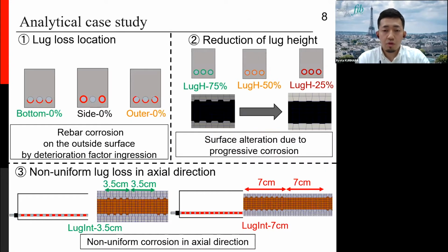To investigate conditions closer to actual corrosion, three viewpoints were considered: the lug loss location, the reduction of lug height, and the non-uniform lug loss in the axial direction. Case 1 supports the corrosion process. The rebar corrosion is caused by the penetration of deterioration factors from the concrete surface. Therefore, the rebar corrosion starts and progresses from the rebar area closest to the concrete surface. In this study, the ultimate case, in which part of the area was perfectly corroded and round in shape and the other area has a sound lug, was analyzed. For the corroded area, three cases were set like these figures, and the red part shows the round shape area.